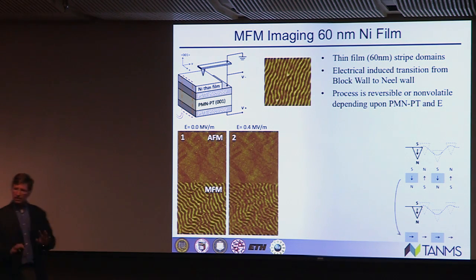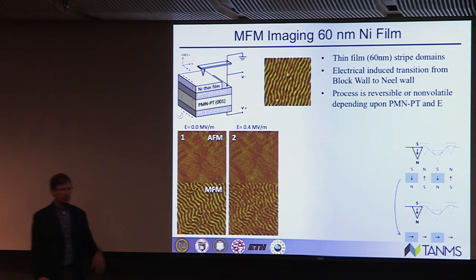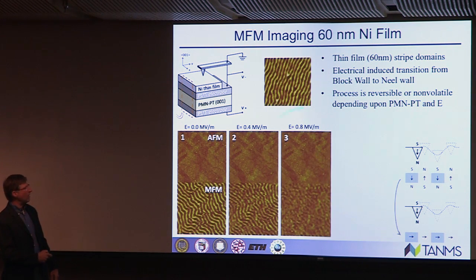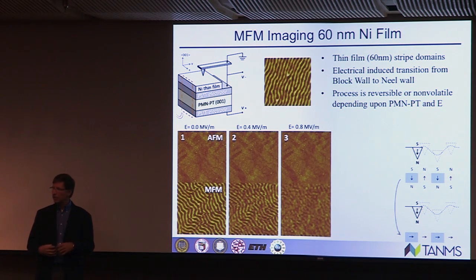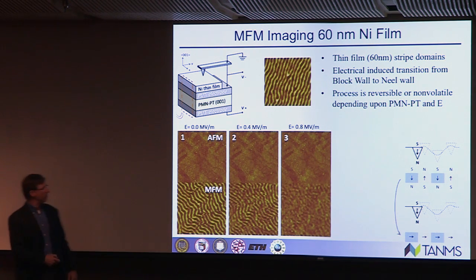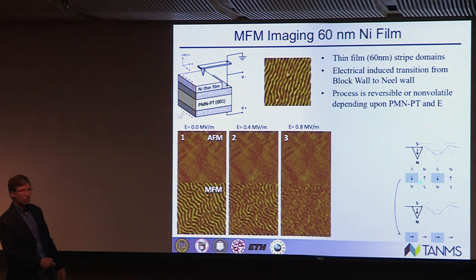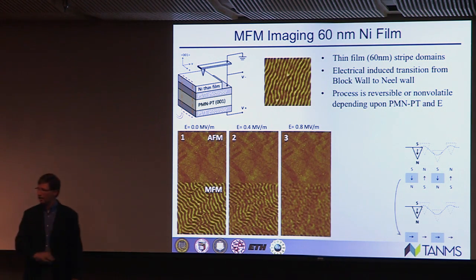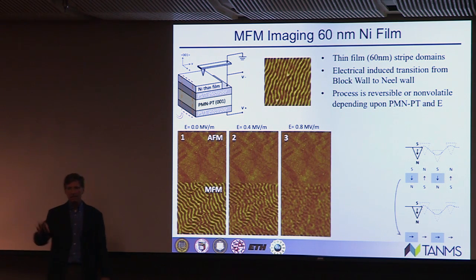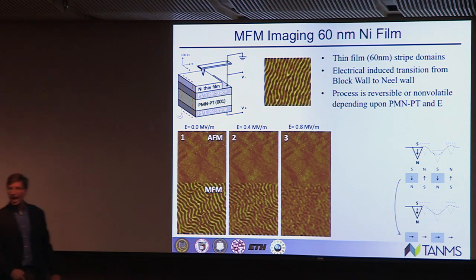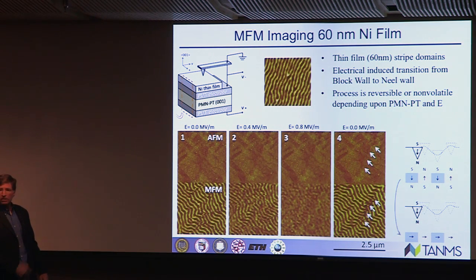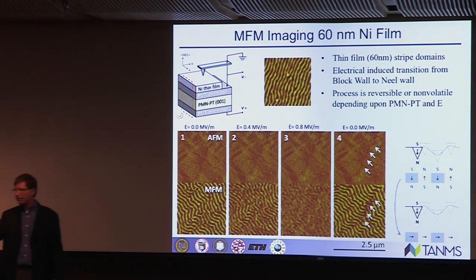Notice down here, everything starts getting fainter, which means the strength of those north and south poles start to vanish. Over here, when we get to 0.8 megavolts per meter, now they've virtually all vanished. So now we've theoretically taken a structure which has north and south poles pointing out of the plane and actually distributed them all to lying in plane, sort of like we had on that preceding slide. Now you say, well, what happens if you take the electric field off? Well, you go back to the original state. Yes, there are some pinning states here due to the domain formation in the ferroelectric. So this looks pretty cool now.